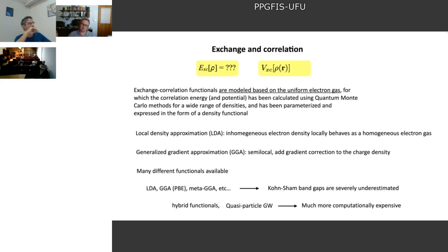If you ask what is the energy of adding or removing an electron, you're going to get about half of the experimental value, essentially. There are ways around it. They are not that old, but not that new as well. The hybrid functionals that mix two theories, Hartree-Fock and DFT, essentially correct part of that problem, which is the electron self-interaction in the LDA or GGA.